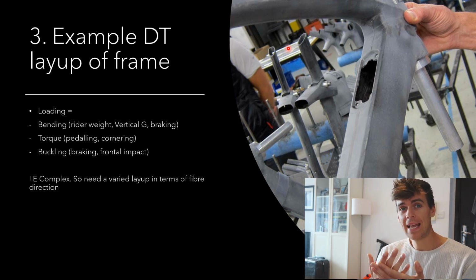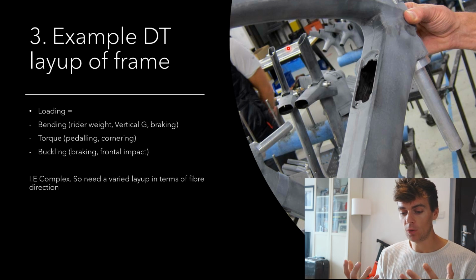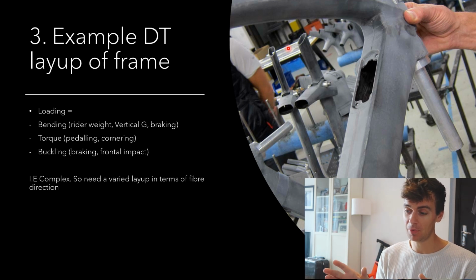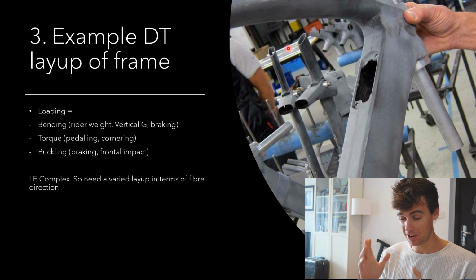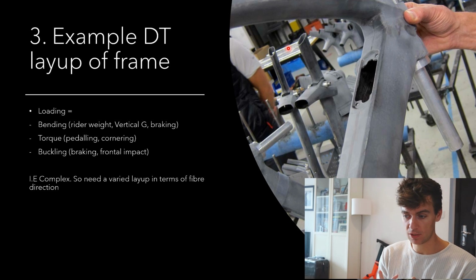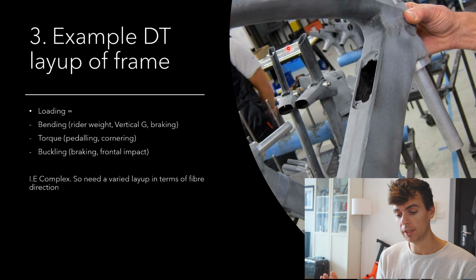So you need a varied layup in terms of fibre direction to deal with all this complex loading. And I guarantee that most of the bike industry engineers don't actually know, okay, 60% of the loading is bending, 40% is torque, or is it 70-30 or 50-50. It's very hard to actually measure these load cases and vary the layup accordingly. So it's kind of a bit of a guess. And if we take a guess, you'll see how easy it is to mess it up.